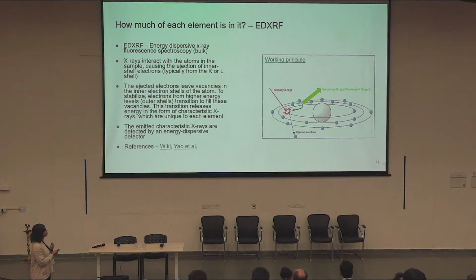So the electrons from the outer shell de-excite to fill the hole that is created by the ejected electron. So the difference in the energy is emitted as the secondary X-rays or the fluorescent X-rays. In this technique, what you do is, you know the wavelength of the primary X-ray, you detect the energy of the emitted X-rays, and with this information, you can get details about what is the element that is present. Because we know that the binding energy of these electrons are going to be fingerprint of the element identity.